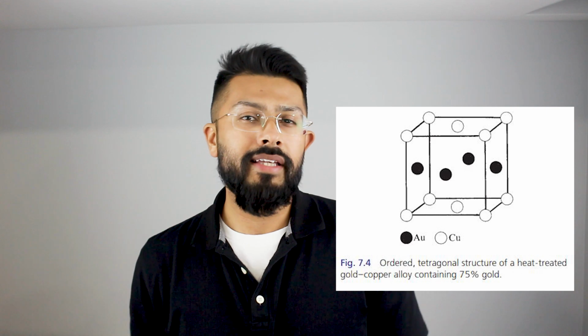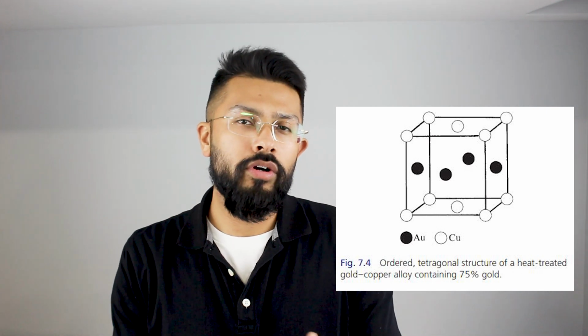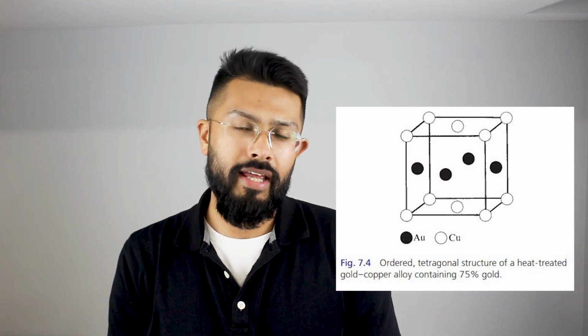Consider, for example, an alloy containing 75% gold, which lies within one of the areas of interest. If this alloy is heated to a temperature in the region of 200 to 400 degrees, sufficient energy is imparted to the system to allow atomic diffusion to occur. Atoms take up their preferred sites and the superlattice is formed. In this case, the superlattice has an ordered tetragonal structure as shown here.